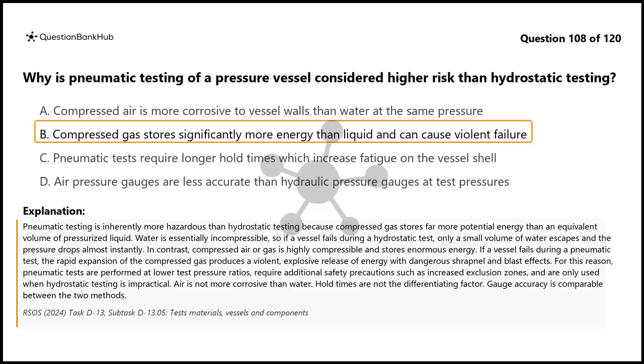In contrast, compressed air or gas is highly compressible and stores enormous energy. If a vessel fails during a pneumatic test, the rapid expansion of the compressed gas produces a violent, explosive release of energy with dangerous shrapnel and blast effects. For this reason, pneumatic tests are performed at lower test pressure ratios, require additional safety precautions such as increased exclusion zones, and are only used when hydrostatic testing is impractical.